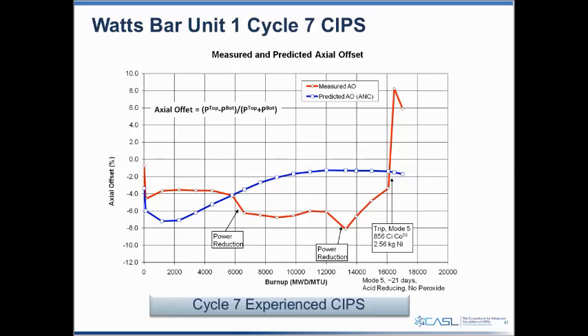During that time, they went to cold depressurized conditions and added a lot of boric acid to the coolant to keep the core subcritical. We were down there for almost three weeks. That actually resulted in dissolution of a fair amount of the crud that had been deposited on the core. So when they restarted, they had much thinner crud, and as a result, they didn't precipitate boron in the crud anymore. And you see that large positive shift in axial offset.